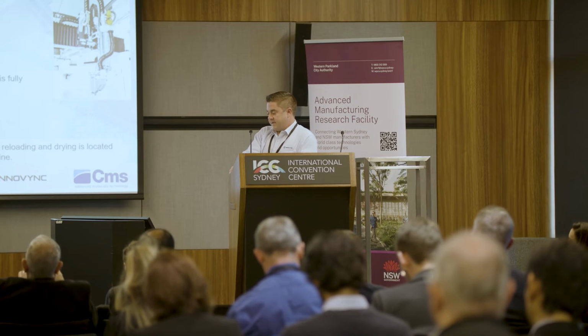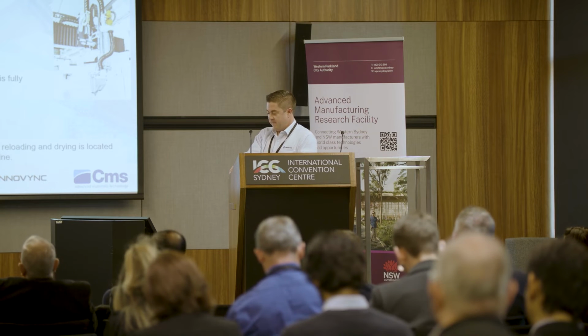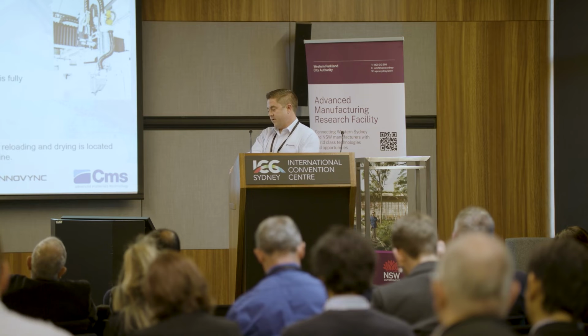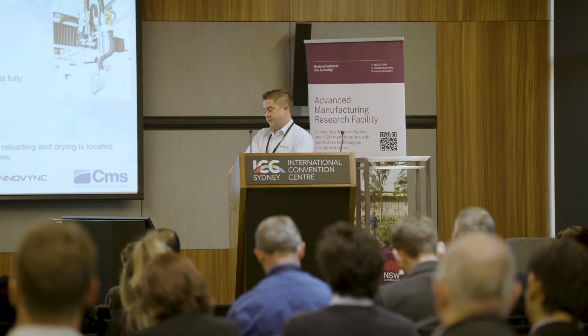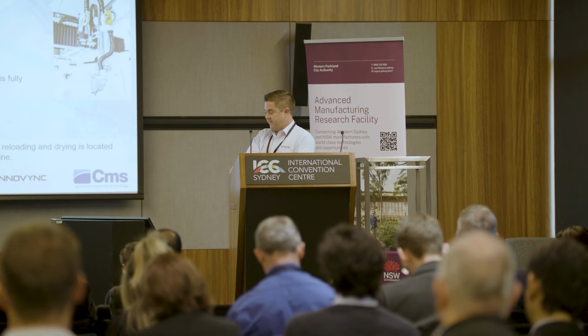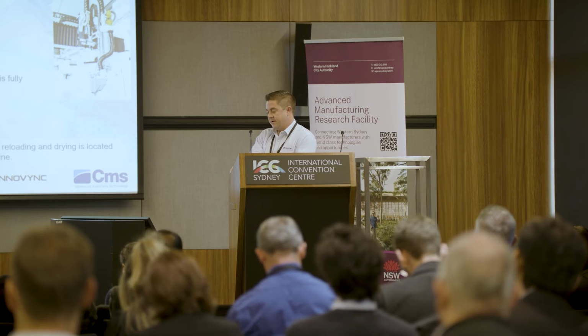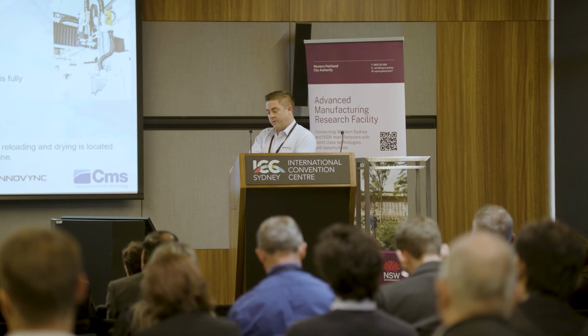The Creator system is designed to quickly build composite jigs, fixtures and tools that are lighter weight than their aluminium counterparts. For example, a carbon fibre PA6 jig can be built in just over 3 hours using Creator and weigh just 14.6 kilos, compared to the traditional aluminium version, which can take up to 8 days to manufacture and weigh 114 kilos. The key for Creator is to control the shrinkage and warpage and maintain good adhesion between the printed layers and control the cooling.